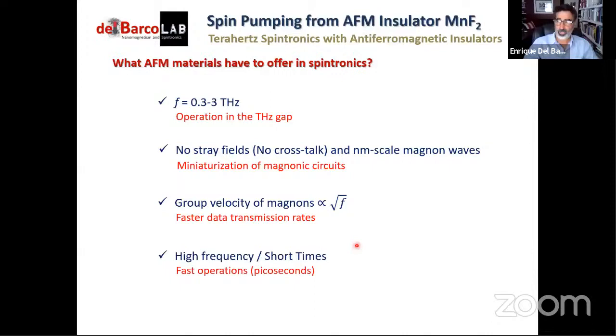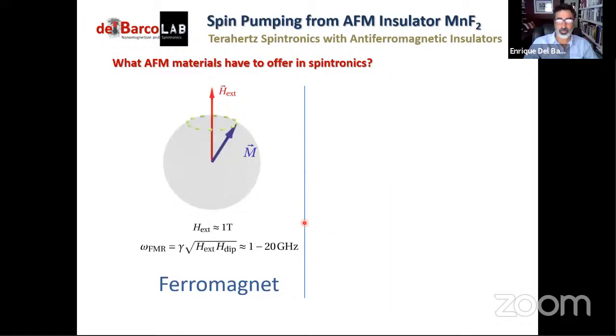All right, so there's something that we're just trying to demonstrate experimentally that is actually easy to see when we compare an antiferromagnet and a ferromagnet when it comes down to magnetic dynamics, right? So if we take a ferromagnet and we talk about ferromagnetic resonance, it's a phenomenon that is very well known in ferromagnetism. We will quickly see that the ferromagnetic resonance frequency is determined by a convolution of the externally applied magnetic field and the dipolar or anisotropy energy, or magnetic fields, inside the sample, right? And with the standard magnetic fields that we can apply in laboratories, let's say one Tesla, it will allow us to work within 1 to 20 gigahertz, let's say, right? This is very well known.